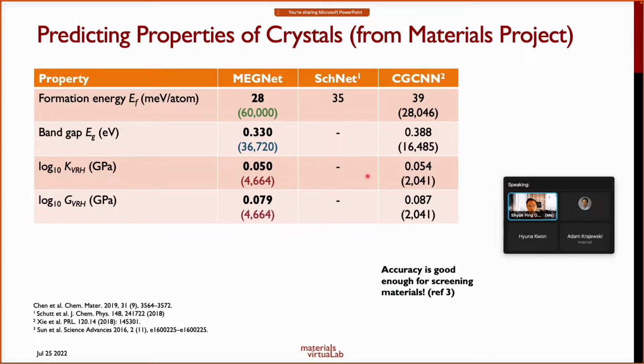Now, we also trained several MEGNet models on the properties of crystals from the Materials Project. Here you will see that, for example, we can predict the formation energy of any crystal to within about 28 meV per atom. This is basically good enough for you to make a lot of decisions about whether something is likely to be stable or not. We can predict the band gap to about 0.33 eV. We can also predict things like the bulk and shear modulus as well, right?